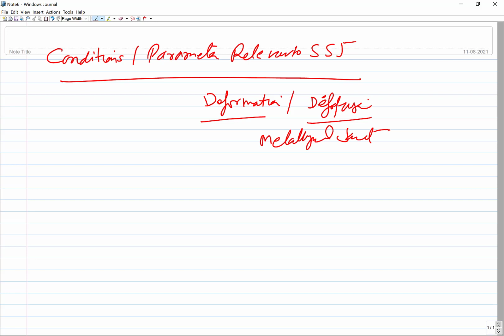Like you take two wires and twist them around each other, then you will certainly get a joint, but that will be totally mechanical interlocking because there is no diffusion across them. So it will remain a mechanical joint, but when diffusion and deformation are both coupled, you will find a metallurgical joint, which is actually needed for a good joint strength.